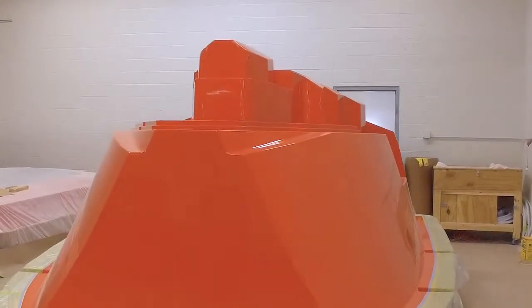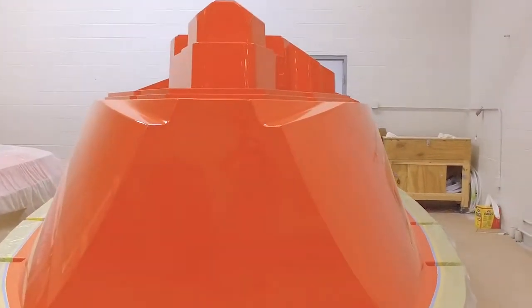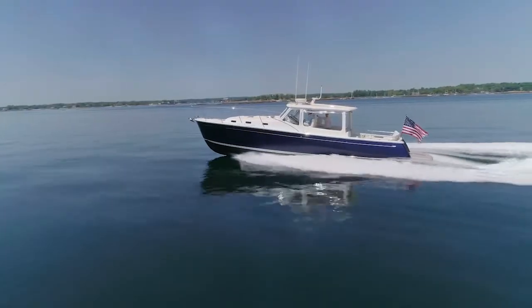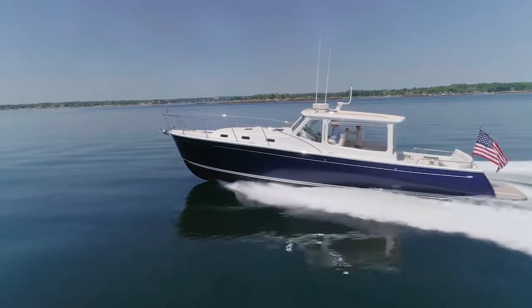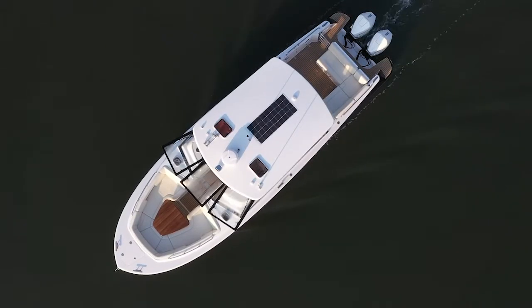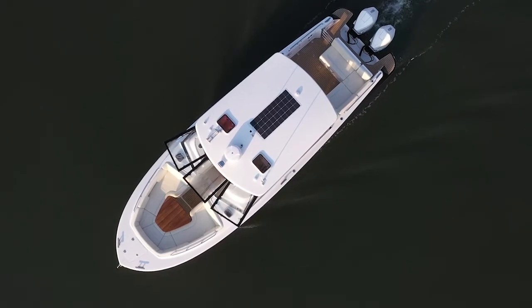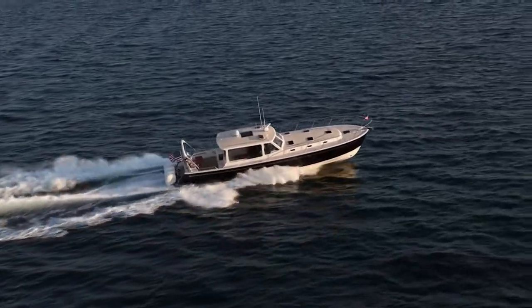We have an epoxy system where after 24 hours sitting in the mold at 70 degrees or so, it's stable enough to demold the boat. Now when we stick it in the oven, we have 26 thermocouples on the inside and outside of the hull. Now we can fully post-cure the boat because there's nothing preventing the heat from reaching the laminate. So it's where the boat will gain its final amount of stiffness and strength. That's something you're going to notice from a performance point of view.